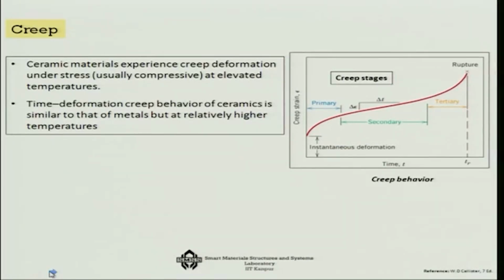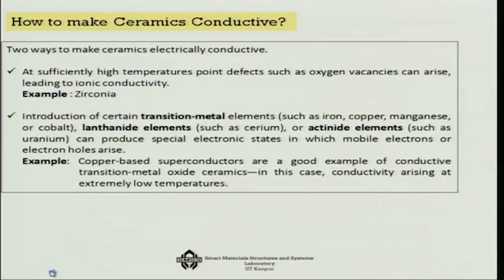The next important thing is the creep, because ceramic materials do experience a lot of creep under stress and at elevated temperature. If you look at this creep, there are actually three parts of it. First is the primary creep, where the creep strain is increasing quite predominantly with respect to time. Then it gets stabilized, that is the secondary part, and once again it increases at a sharper rate in the tertiary region. As the time continues, this happens at a sharper rate towards the end. So, that is the nature of creep in the ceramic materials.